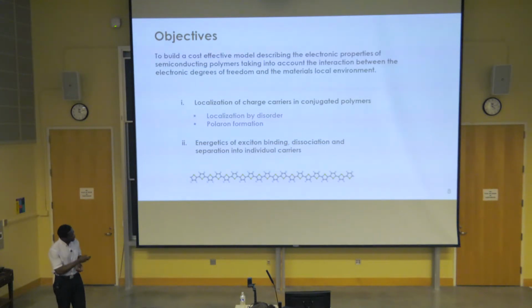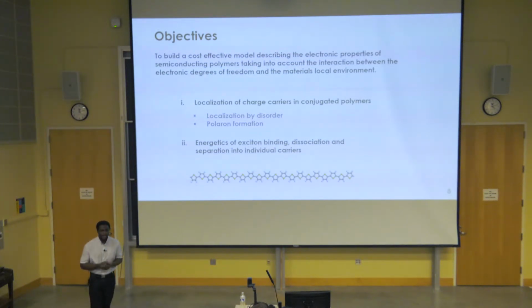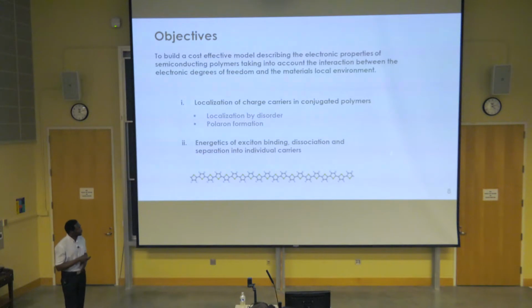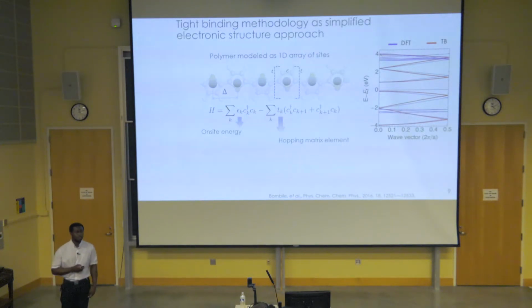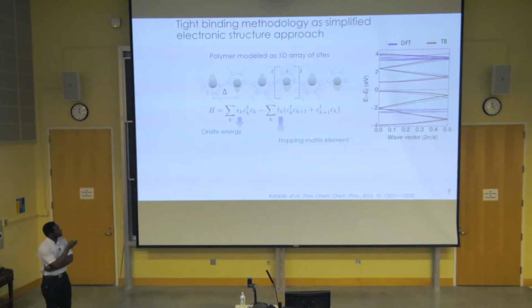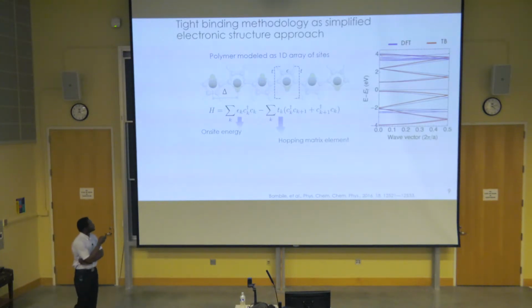And my study will focus on this polymer here, polythiophene, as a model case. It was one of the most studied polymers in this field. And so the model that I'm using is based on the tight binding approximation. It is a semi-empirical model, and within this approach, a polymer chain is considered as an array of sites, and each site corresponds to an entire monomer unit. So we are coarse graining at the level of an entire monomer unit.